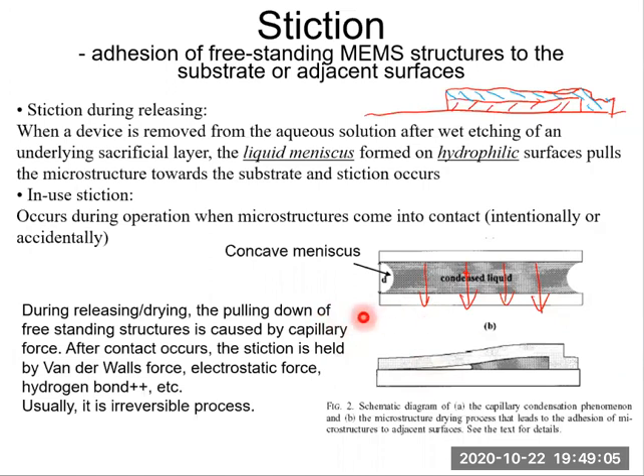Right, so the stiction is irreversible. If it occurs, it occurs. You cannot reverse the process when it's completely dry. Any question? This is a very important feature of stiction. It's typically not reversible. Again, I want to emphasize that the initial contact is caused by the capillary force, by the meniscal force. But the stiction is held by other forces such as the van der Waals force, electrostatic force, and the hydrogen bond. Questions?